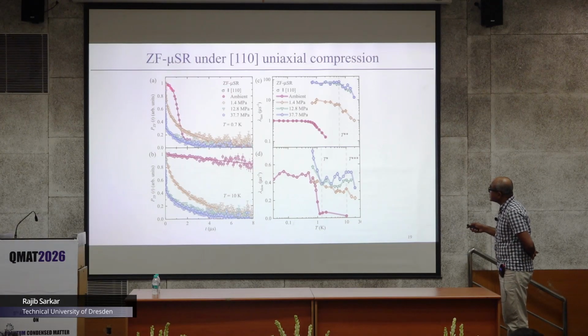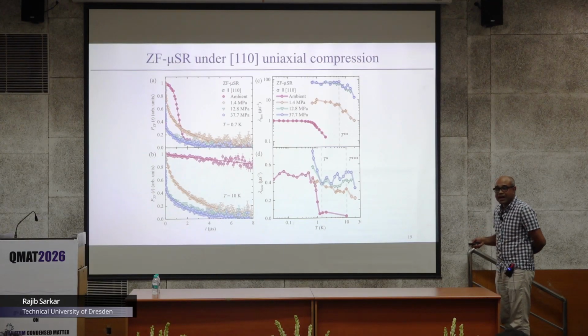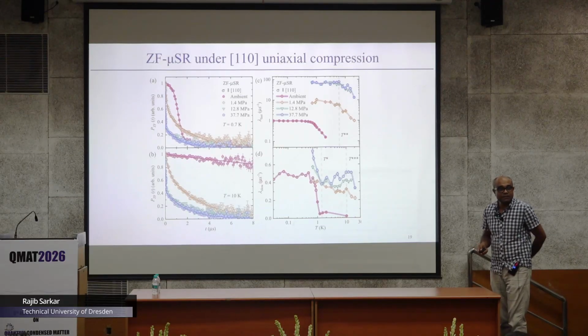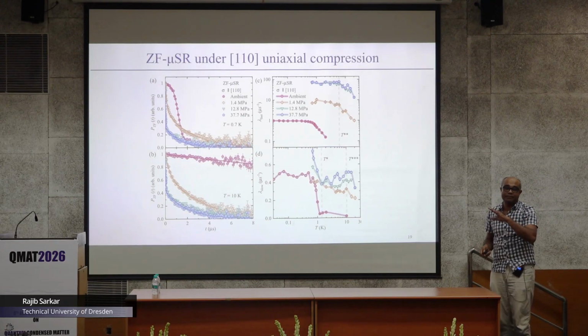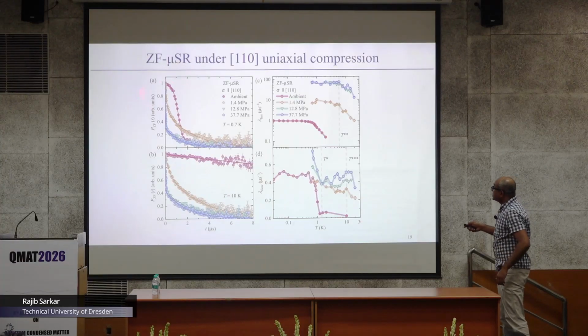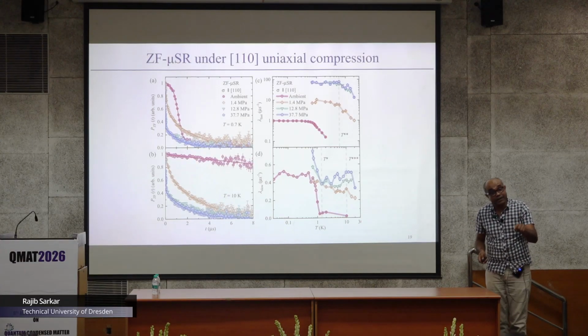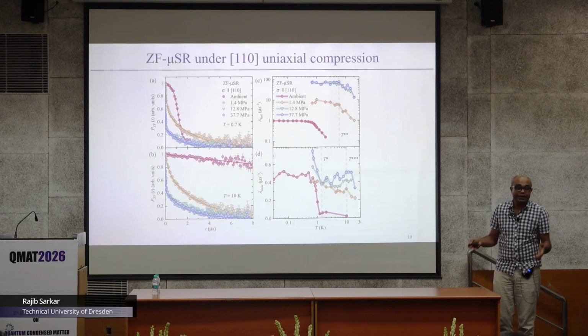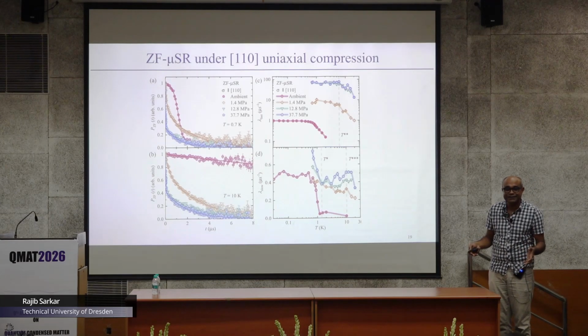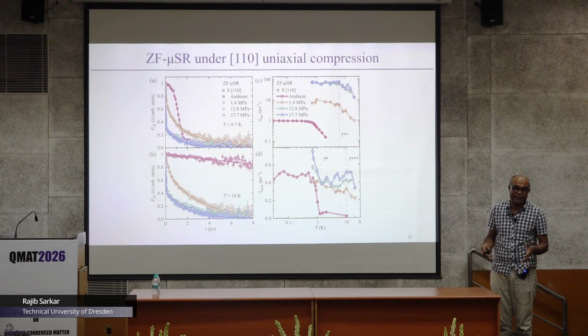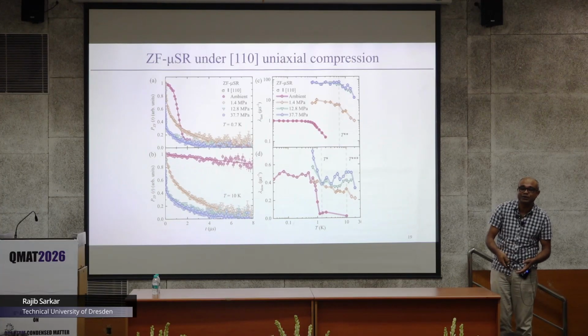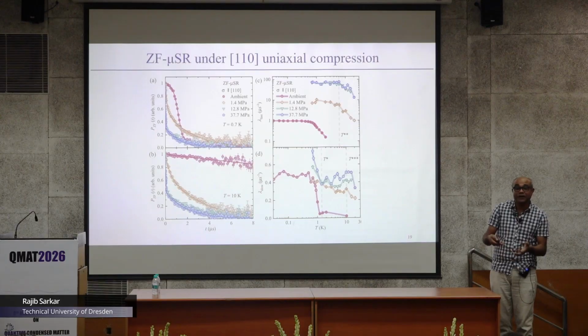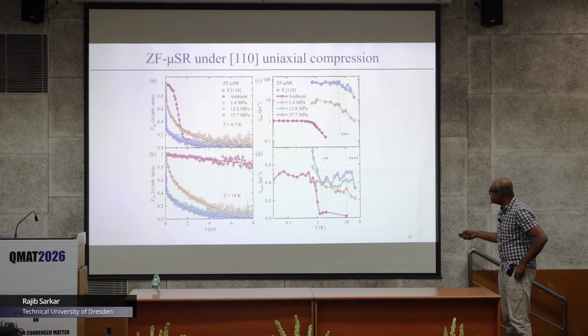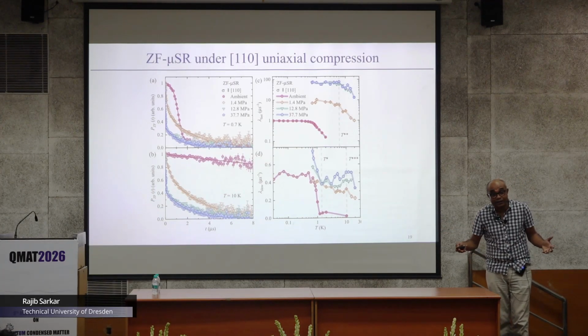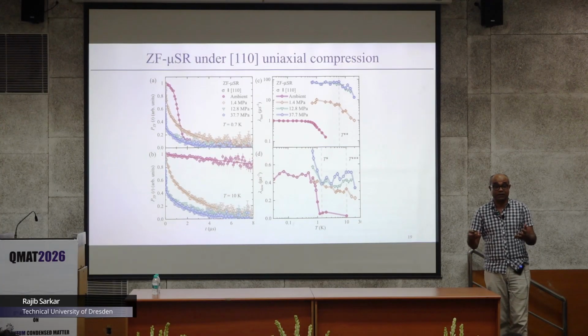As you increase the pressure, you see the relaxation start to increase a lot. That means there is a very fast damping happening. This is at 0.7 Kelvin. Unfortunately we cannot go to 20 or 30 millikelvin, because it is experimentally very challenging: if you go to such a low temperature, there is a huge heat load that jeopardizes our experiment. And now this is at 10 Kelvin, which is far above any kind of ground state.